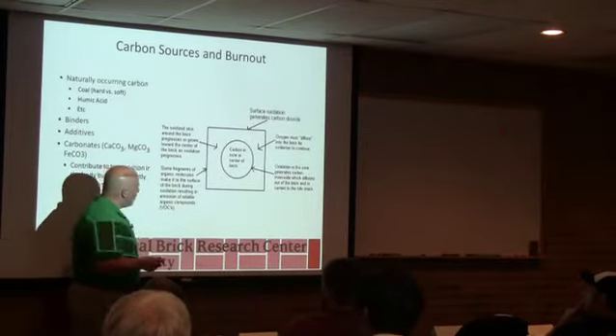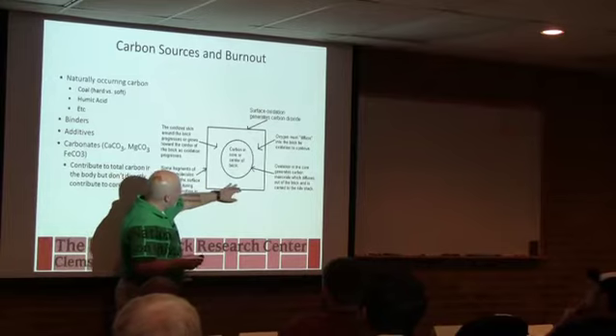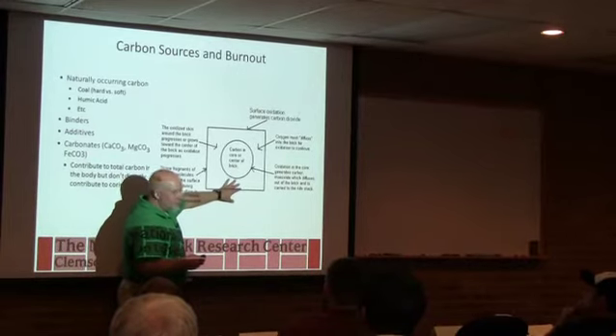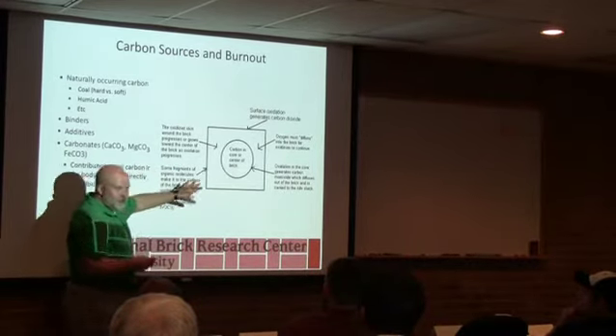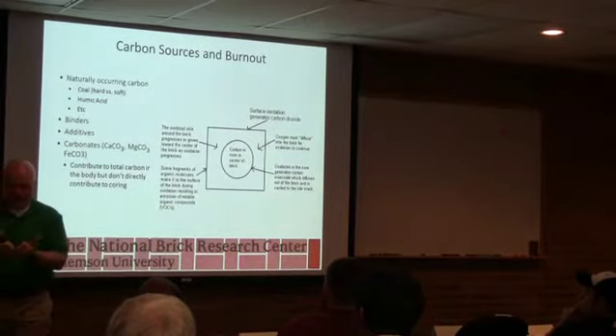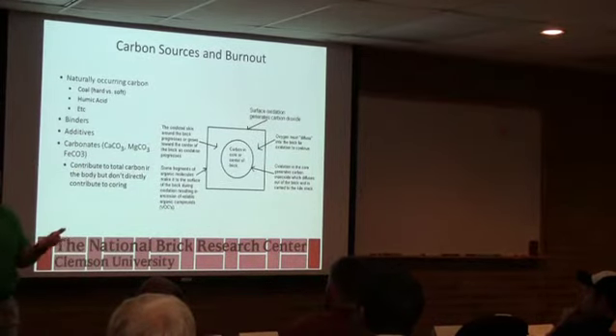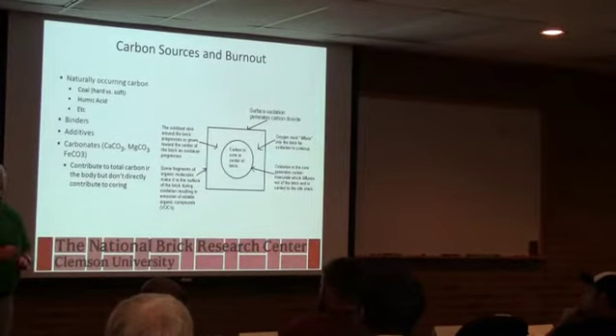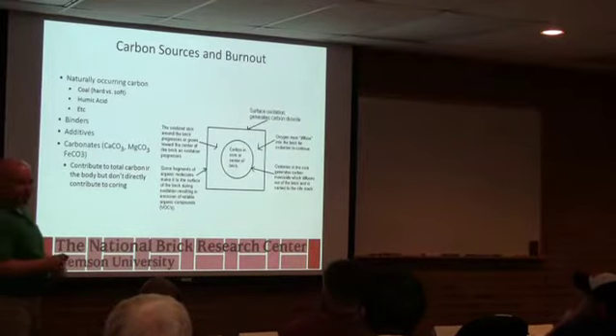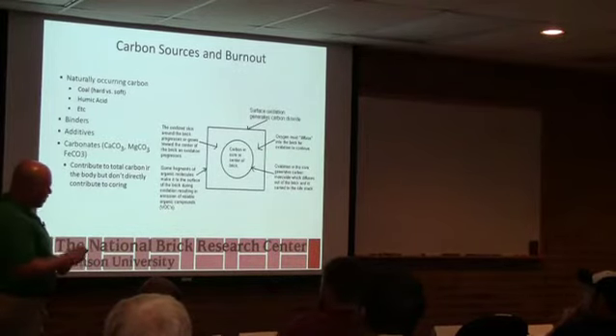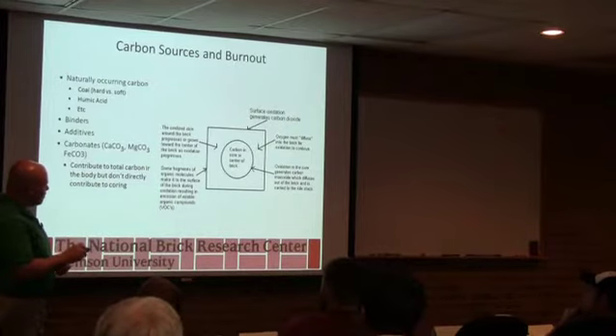And there are times, I'll show you some thermal analysis when we get to firing, but there are times like when the clay mineral decomposes. There's enough gas pressure from the water trying to leave that's generated from the clay mineral that all combustion stops. You don't see any carbon burnout during that period. So a lot of things go on to remove the carbon, and there are tricks you can play.